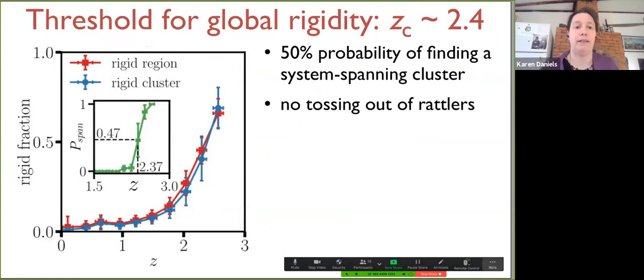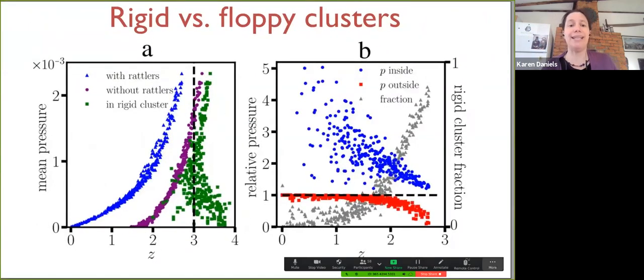And we find that the threshold for the global rigidity, using the pebble game analysis, is about Z equals 2.4. So this is below Z equals 3. And as such, it sure seems like maybe these mesoscale structures are what's controlling it. These are things that are not just system-wide averages. They're very specific to the structure that you have. And that seems to be what's controlling the global rigidity. We of course can do clusters where we either include the rattlers or we don't. And we can look at how the pressure is different inside the rigid clusters and not.